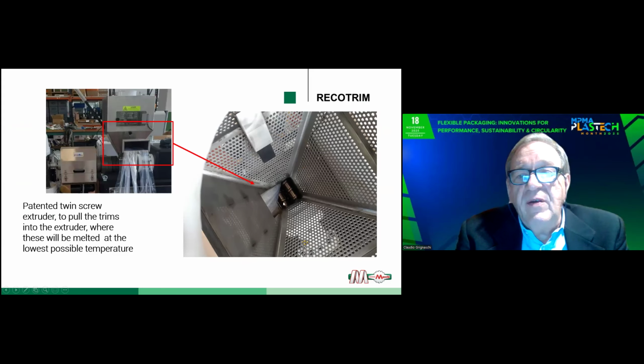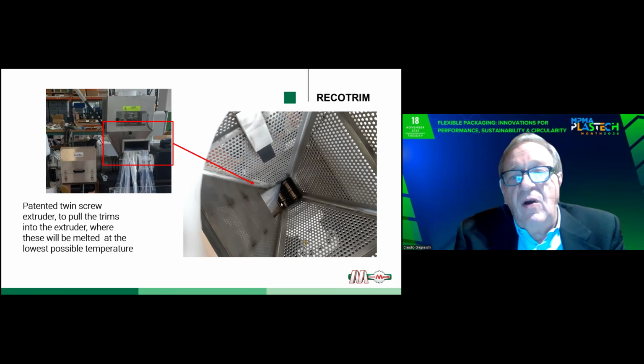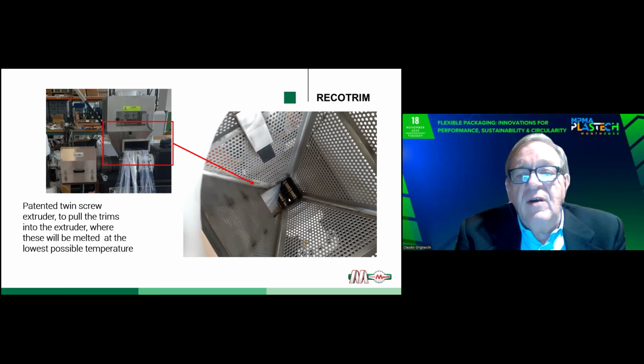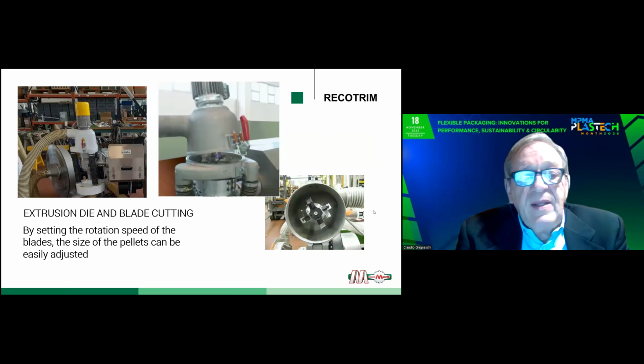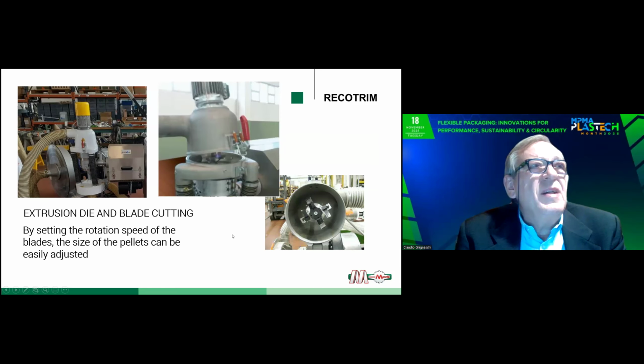As you see here, you can see a particular of the twin-screw extruder, which allows to pull the trims in the extruder constantly, independently of the feeding speed. Blade cutting on top of the strand die. By adjusting the rotation speed of the blades, the size of the pellet can be adjusted easily.